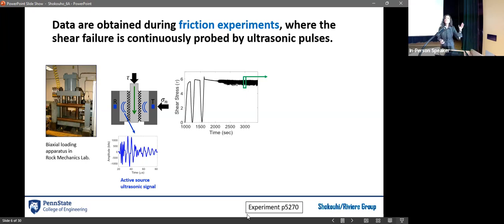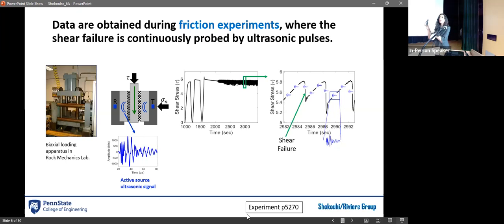So what does the data look like? If you look at shear stress evolution versus time, at the end, forget about the beginning, you see these really small cycles. These are stick-slip cycles of friction. The beauty of these experiments is that through this collaboration with Chris Marone, we can create irregular cycles, and we can create many of them. He knows how. So what we do is we monitor with these blue lines throughout the experiment how the state is changing.